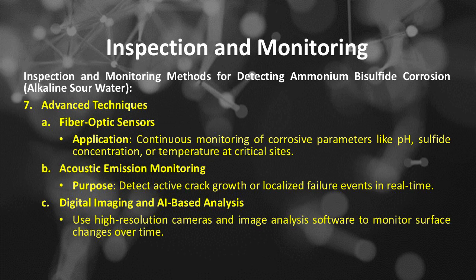Inspection and monitoring methods. Number 7 is advanced techniques, which includes, number A, fiber optic sensors. Its application is continuous monitoring of corrosive parameters like pH, sulfide concentration, or temperature at critical sites. Number B, acoustic emission monitoring. It is purposed to detect active crack growth or localized failure events in real time. Number C, digital imaging and AI-based analysis. It uses high-resolution cameras and image analysis software to monitor surface changes over time.